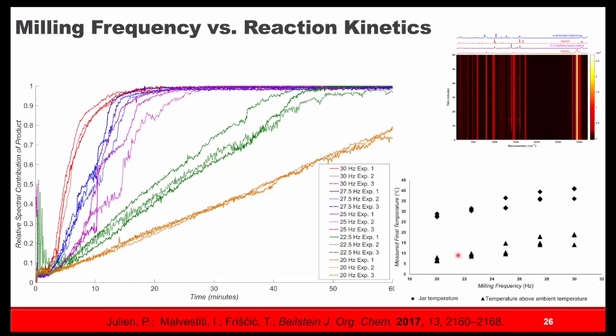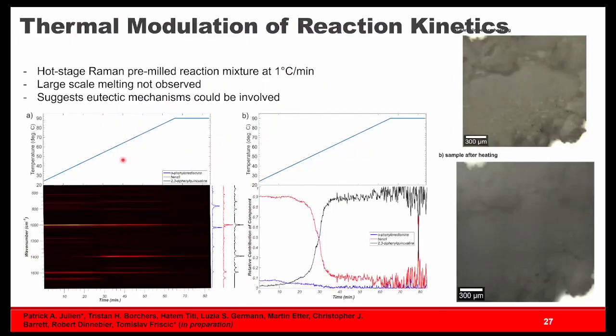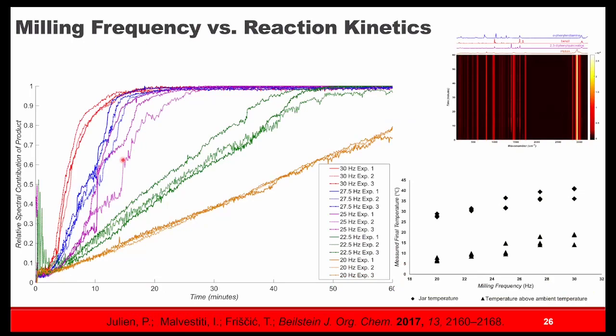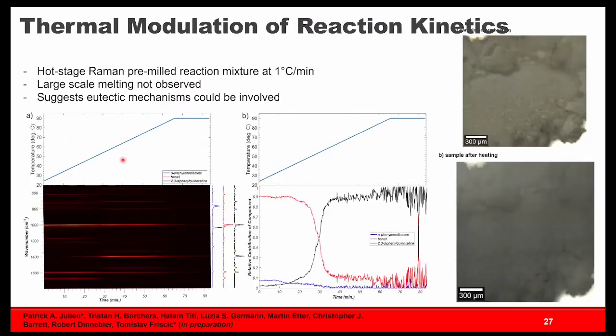We're only about 10 to 15 degrees Celsius, or maybe close to 20 above room temperature when the reactions finish. But we thought this change in the kinetic profile was really interesting to look at, right? And what might be causing that. We were really thinking that, well, the temperature changes here are quite small, but are they significant enough to change the chemistry?